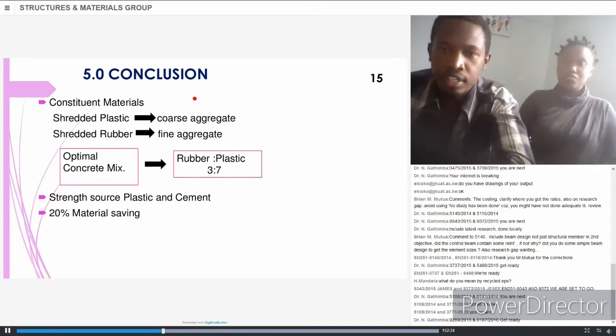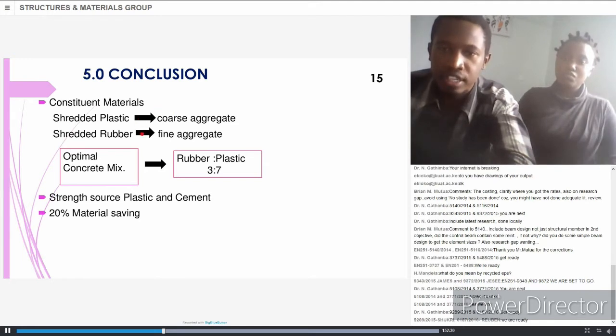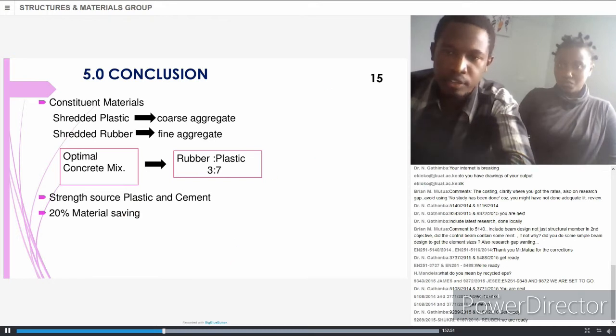So as I conclude, we found out that the shredded plastic performed as a coarse aggregate since it had relatively larger particles compared to that of rubber, which had relatively finer particles. The optimal mix for the rubber plastic combination had a ratio of 3 to 7, or 30% rubber and 70% plastic. The major strength was being sourced from plastic and the cement, as exhibited from the results, and 20% of material saving was witnessed, as shown in the area of steel required and the steel provided in the slab design.